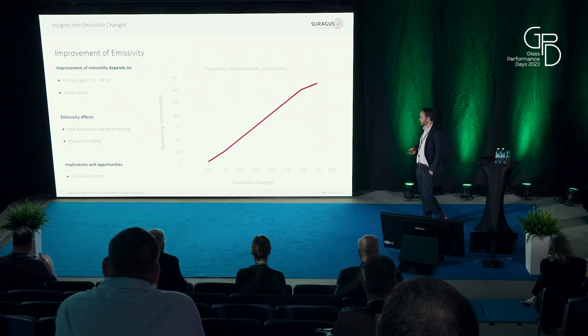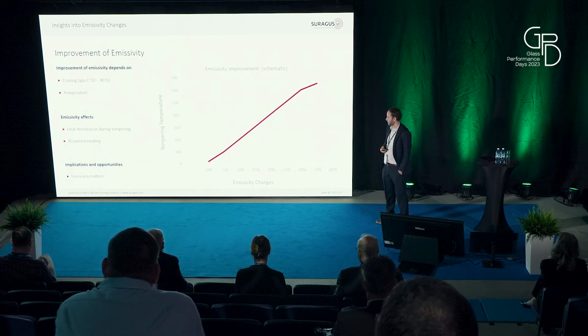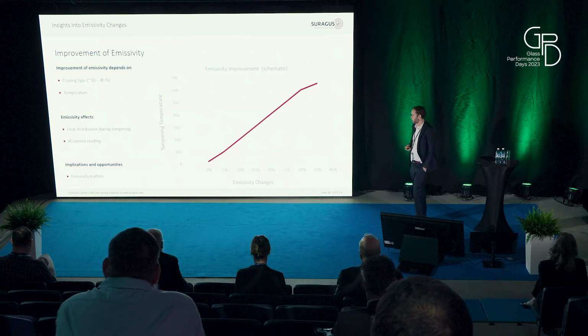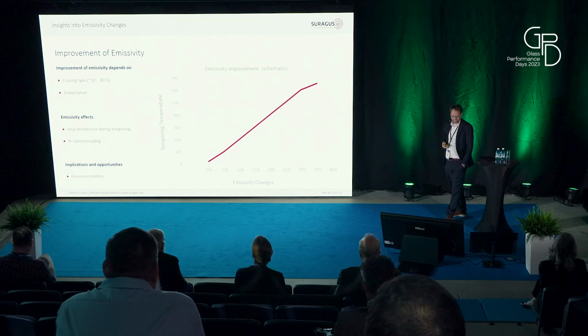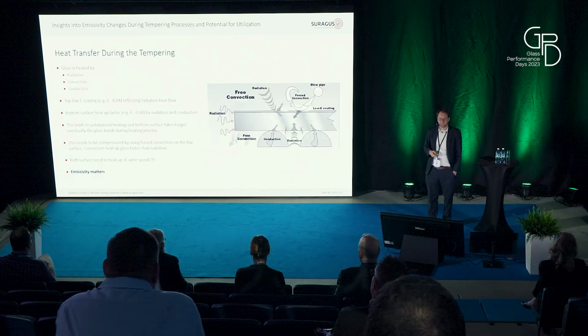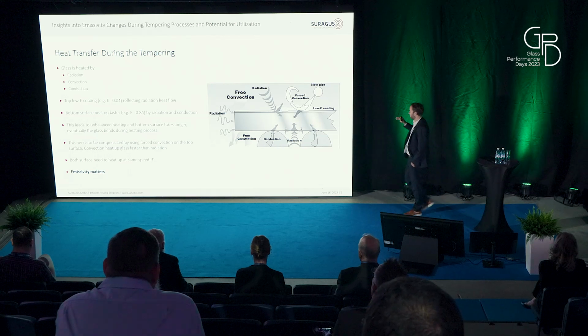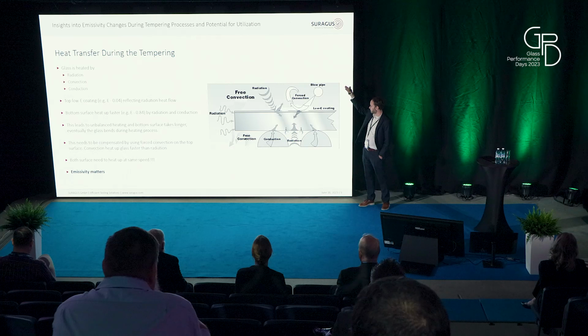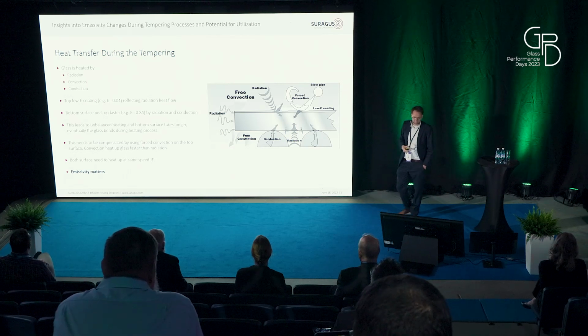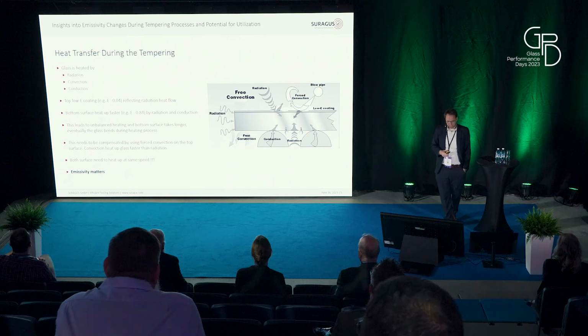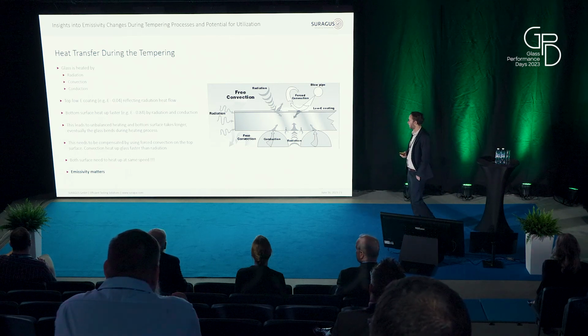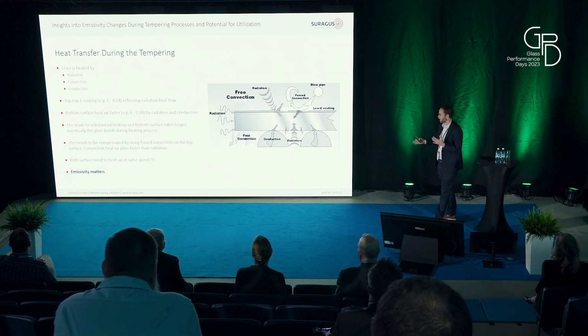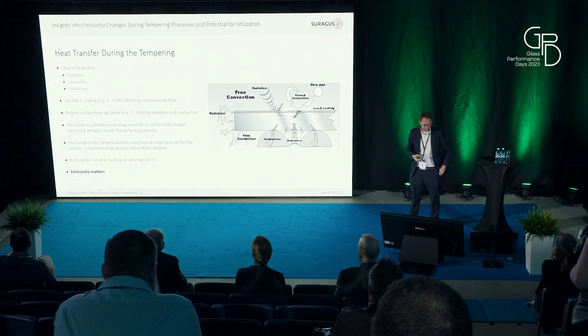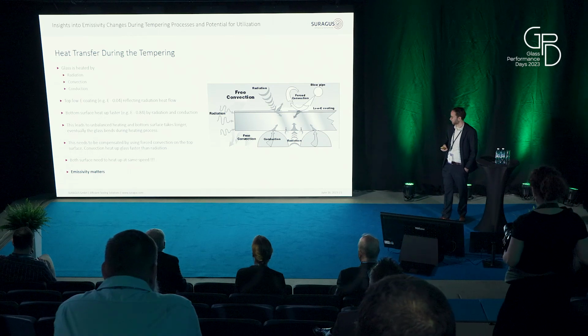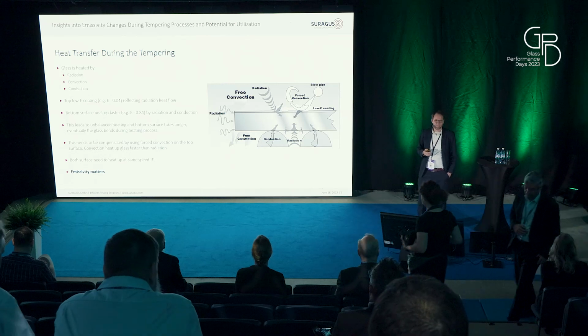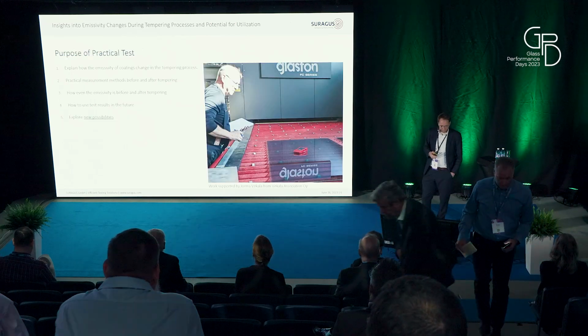The emissivity affects the heat distribution during the tempering, and this is very important. And it also affects the infrared camera reading. So the short version is emissivity matters, and it's clear that if I have an emissivity coating on top, the heat distribution is different from top and bottom. So furnace makers operate with different ways: radiation, convection, thermal conduction, to level that. The aim is always to have the same heating from the top and from the bottom, so you have optimized stress induction. And again, emissivity matters, and we've been discussing this for several years here at GPD,